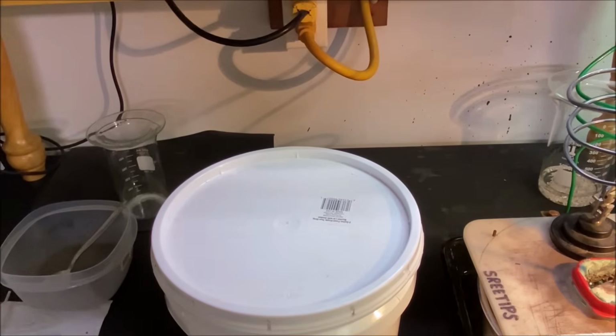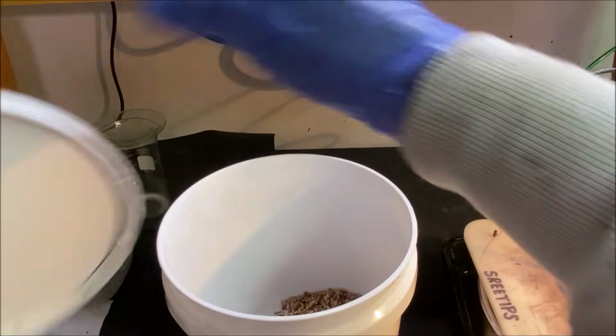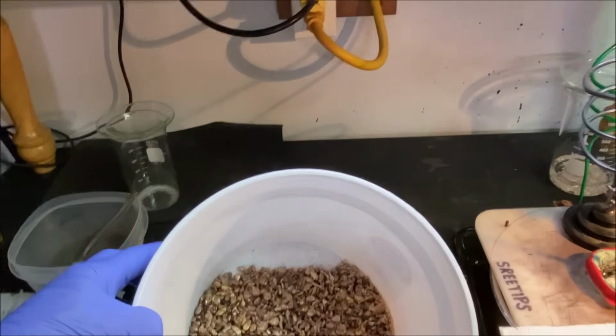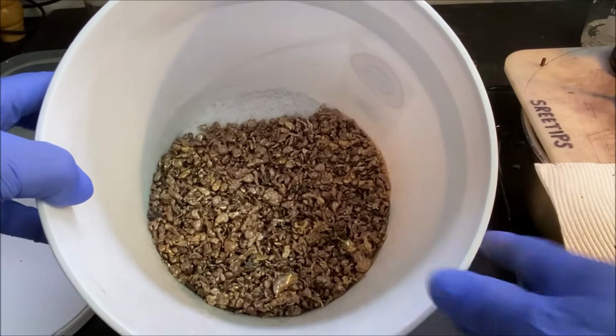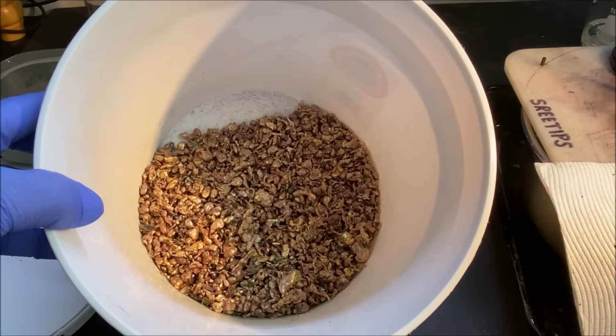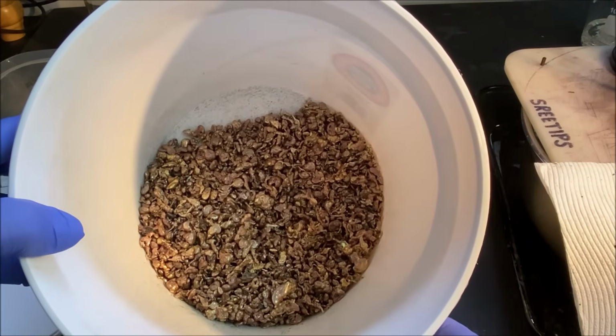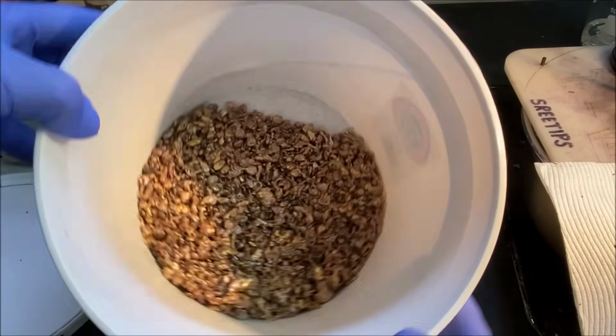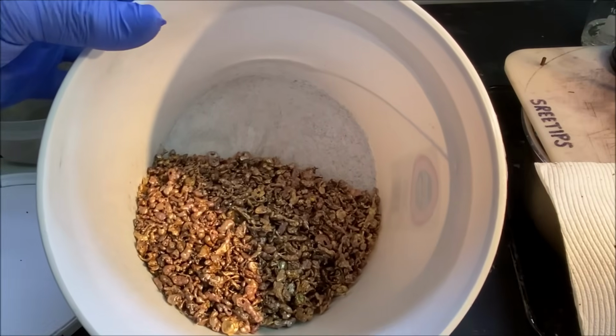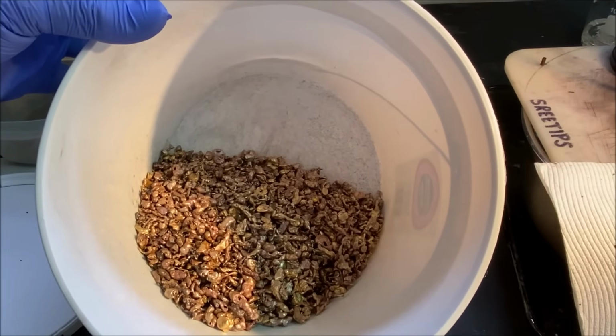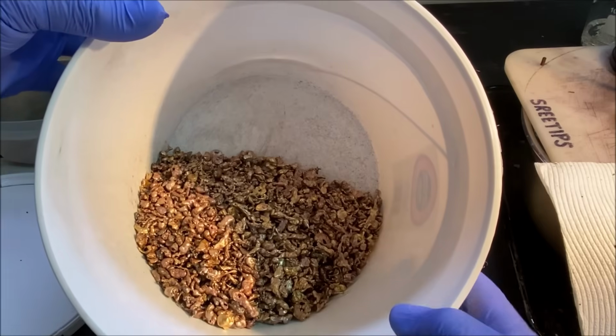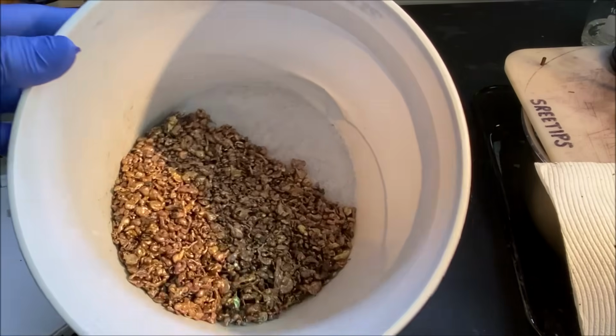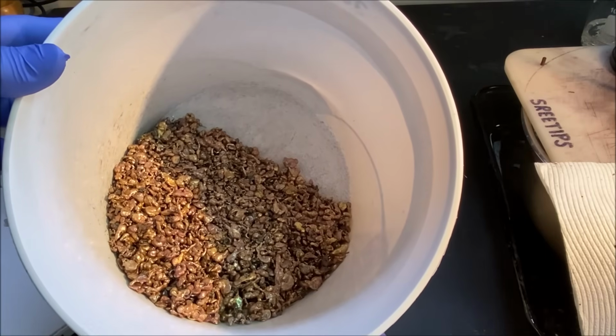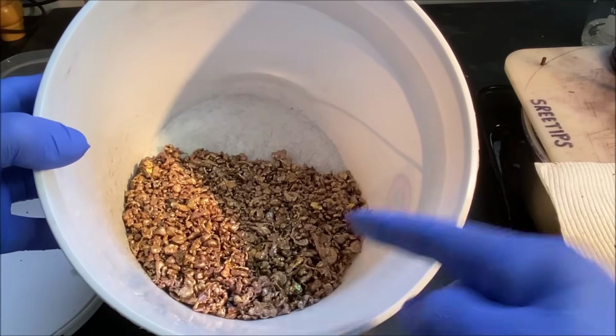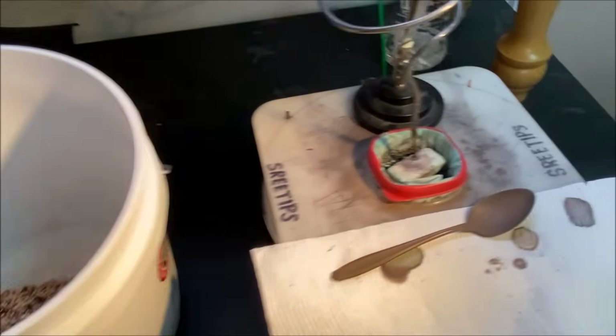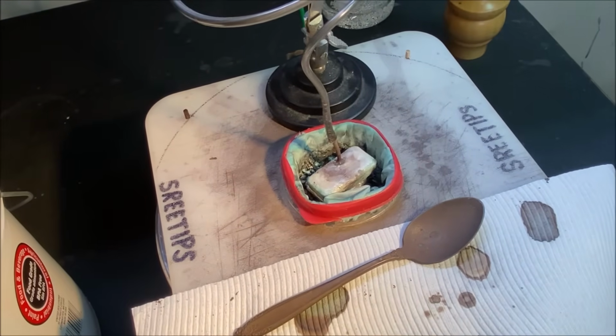And what I've got is this bucket down here is full of impure silver. That's probably about 6 or 7 kilos of impure silver from my gold refining. When I refine gold, I use sterling silver, and I use nitric acid to pull the sterling silver back out of the gold, and then I recover the silver from that, melt it into shot, and this is what I use as feedstock for the electrolytic silver cell.